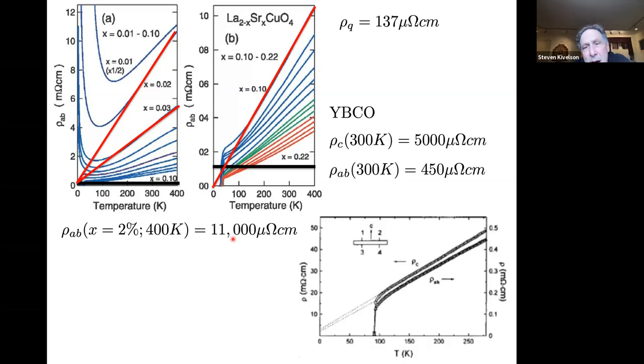Here's YBCO, often considered to be the gold standard of the cuprates. This is optimally doped YBCO. YBCO, unlike most of the others, is only about an order of magnitude anisotropic between the in-plane direction and the out-of-plane direction. You can see here that the resistivity is more or less linearly increasing with temperature, both in-plane, rho AB, and perpendicular to the planes, rho C.